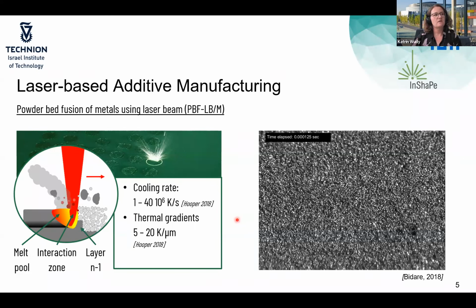And what you can see is that there is a homogenization of the dynamic of the process. So there is no spatter formation and no balling effects visible. And what we have further conducted, so we have seen with our standard diameter of our Gaussian beam profile and ring-shaped beam profile, and what we have conducted at TUM to increase the diameter of our beam profile with an additional zooming axis on our scanning system. So we can zoom, we can increase the size of our beam profile by a factor of 2.